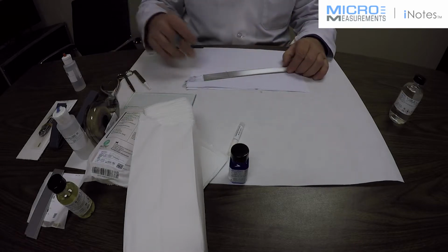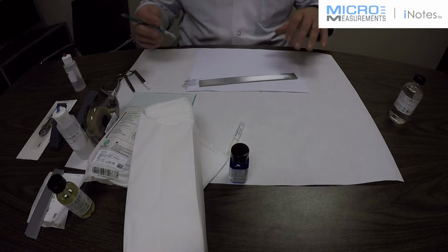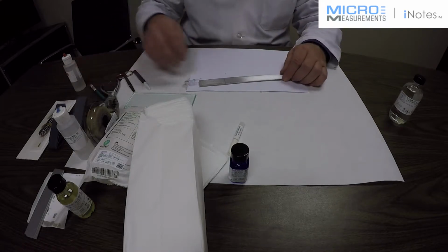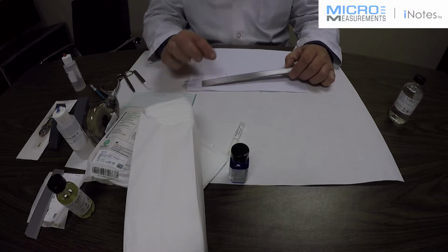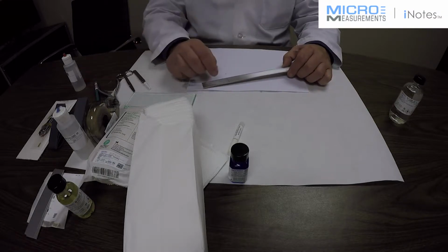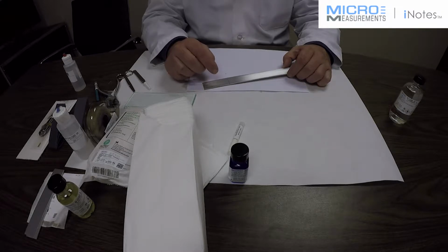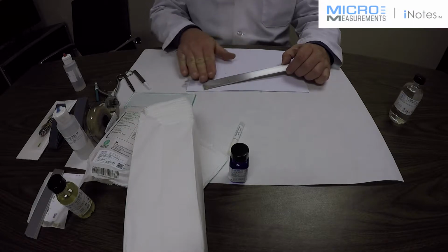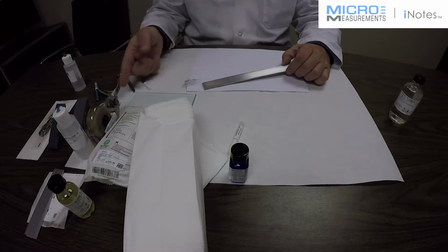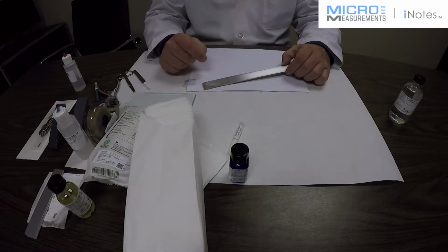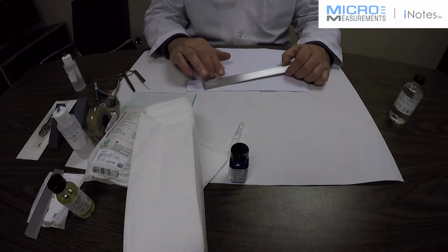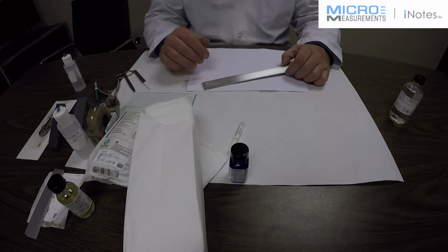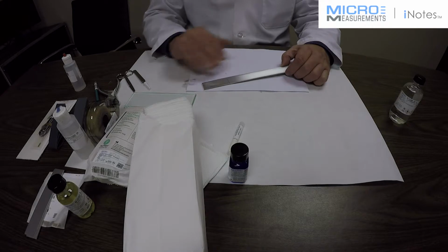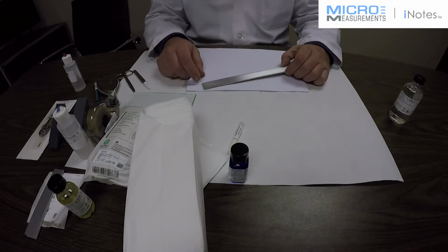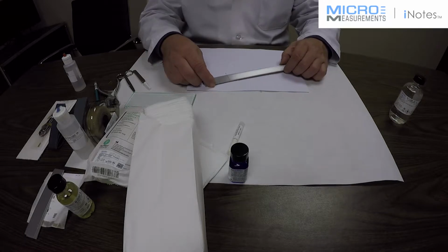Now, if you read our tech note on strain gauge surface preparation, it goes into a lot of detail on the reason I'm doing some of these things now on aluminum. I'll tell you why we use a 4H pencil, is because we want to produce a burnish. We don't want to scratch the surface. We don't want to use a tool or something that's going to dig into the aluminum. On the sanded surface that we just created with the silicon carbide paper, this 4H pencil will flatten some of those peaks, so that when I remove the pencil lead later, it's going to leave behind an optical line. It's called a burnish, but there's no surface deformation or strain concentrations created. And that's very important when we're trying to measure strain.